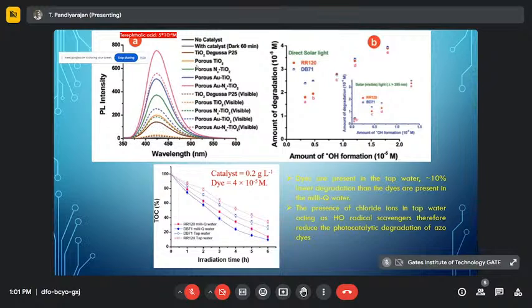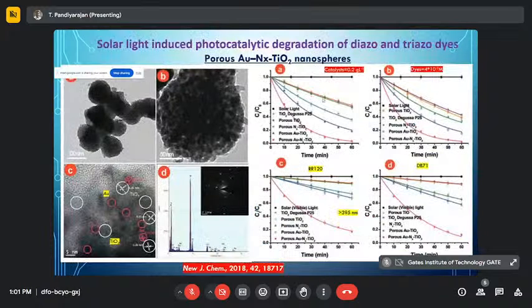Then with the different kinds of material, the OH radicals start to increase. But upon visible light, the OH radicals are increased enormously. Around 90% of OH radicals are produced in the porous gold and nitrogen doped titanium dioxide material. Okay, so the OH radicals are highly appreciable in the case of the combination of gold and nitrogen doped titanium dioxide. That is why you are getting very fast and highly efficient degradation.